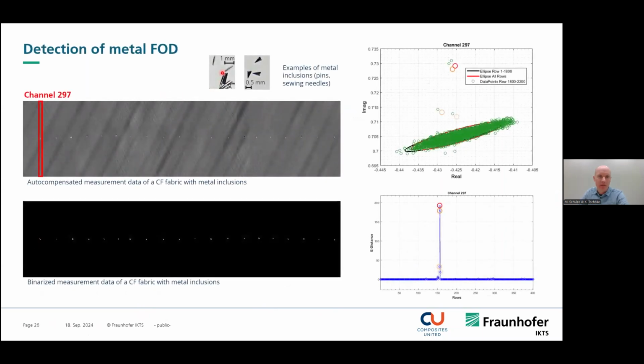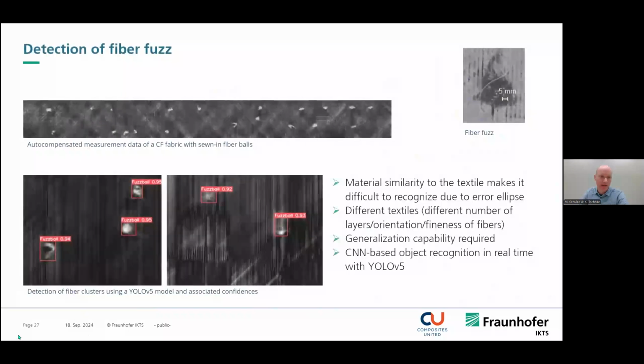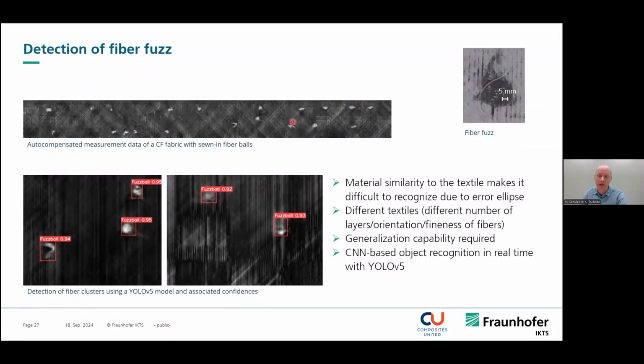We find pins, so metal insertions. So if there's a broken needle, that's quite easy because its conductivity is much higher than the carbon fiber. We find fiber fuzz that can fall on the fabric. Therefore, we also use machine learning algorithms. So that's quite impressive how it works. So it's very easy to detect these fuzz balls.